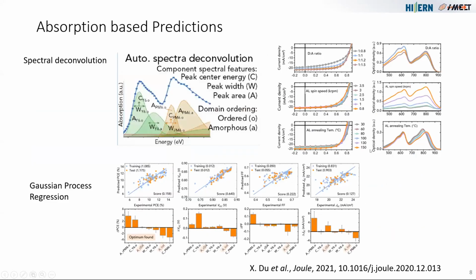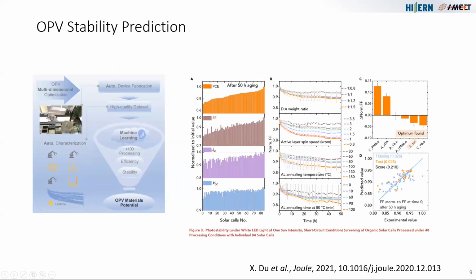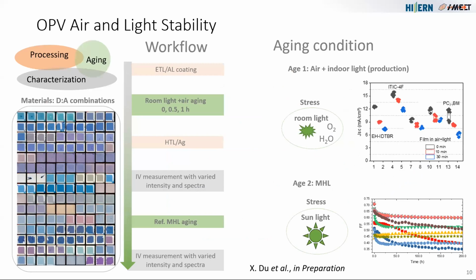So here we already had the features extracted, and we now degraded the solar cells that were processed under different conditions, and then correlated the absorption features together with the stability. And also here we could get a very good correlation. We were then moving on from this approach where we were changing the processing conditions to approaches where we are starting to change the active layer compositions. And with this pipetting robot and the automated fabrication, here we did a series of 50 to 60 different donor and acceptor combinations. And for each of these donor acceptor combinations, we tested 2 degradation conditions.